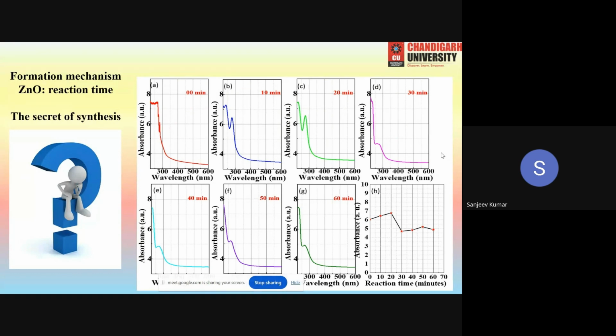You have to stir for 20 minutes, 10 minutes, 40 minutes, 60 minutes, or 100 minutes. A very difficult task. Most of the students or the researchers let it be for 2 hours, 3 hours, 4 hours, or the whole night. But with the help of UV visible spectroscopy, you can easily monitor these.